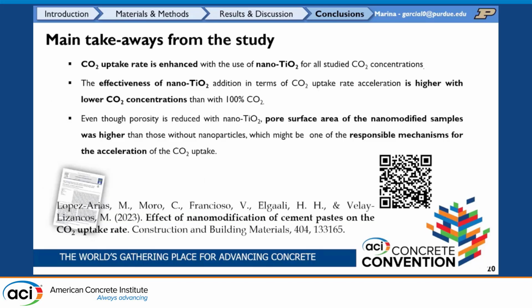In the conclusions, or the main takeaways of this study, we saw that the CO2 uptake rate is enhanced when we add titanium dioxide nanoparticles for all CO2 concentrations. However, this effect is more significant when we have lower CO2 concentrations. And we saw that this may be due to the refinement of the pore structure, where we do have lower porosity, but our pore surface area is increased.